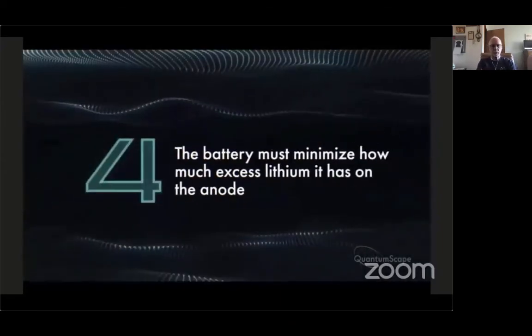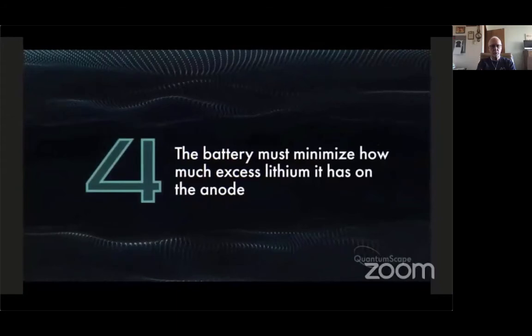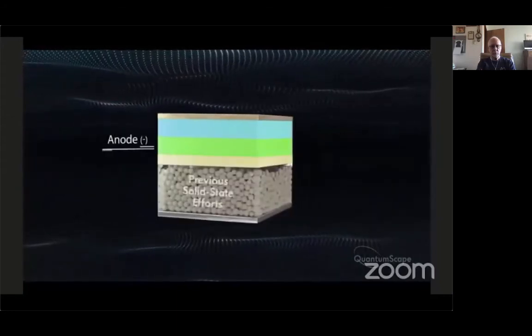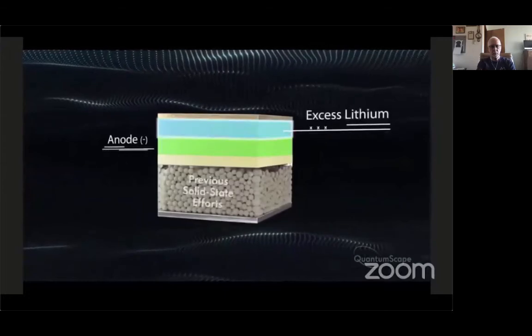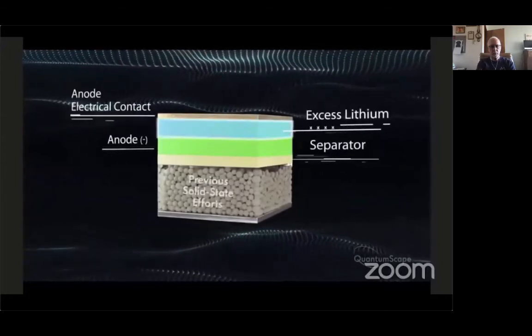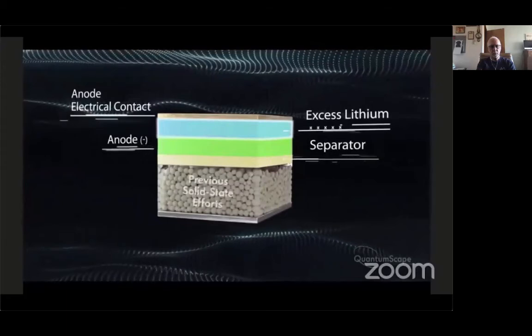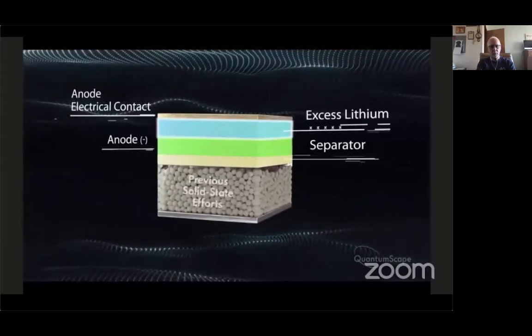4. The battery must minimize how much excess lithium it has on the anode. Many solid-state designs require a layer of excess lithium between the separator and the anode electrical contact to make it easier to deposit lithium on the anode and prevent dendrites from forming.